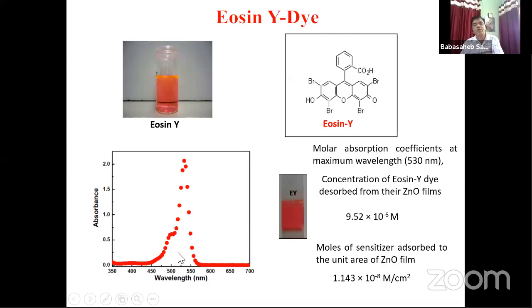Whenever you want to use TiO2 for a dye-sensitized solar cell, you need a dye with an NCS group, which can attach very well to the TiO2. But whenever you are thinking about zinc oxide, you should have a dye with a carboxylic group, which can attach very well to the zinc oxide. So we have used eosin Y dye, which has this carboxylic group, that is the COOH group, which can attach very well to the zinc oxide.